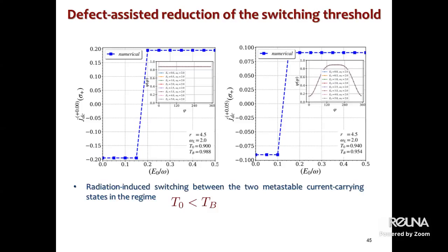So what is the physical mechanism behind that? Near the branching point, as I showed in the previous slides, the free energy landscape softens. The barrier between two current carrying regimes is reduced. And therefore, a smaller inverse Faraday-induced effective amplitude, or let's call it effective bias, is sufficient for deterministic switching.